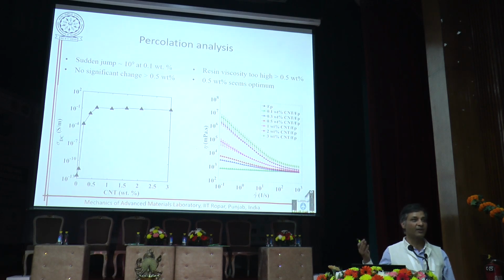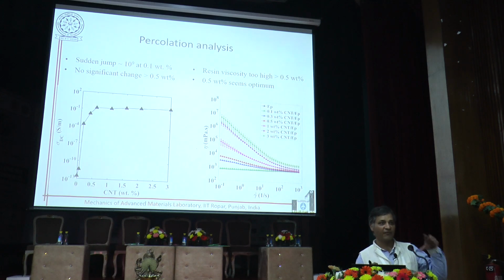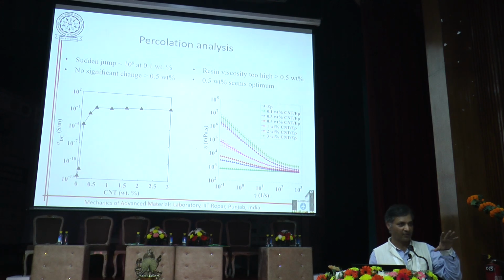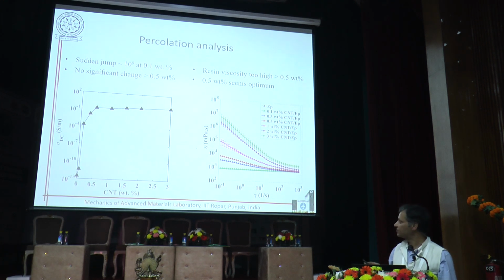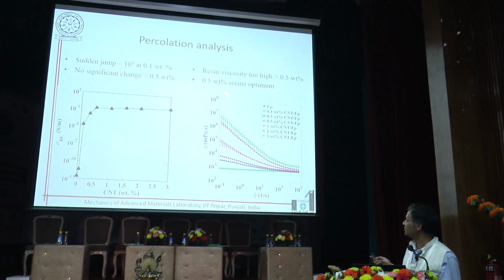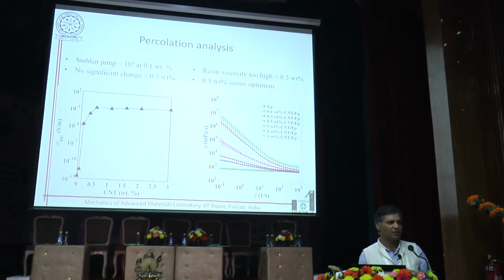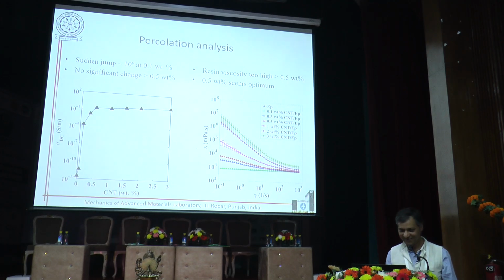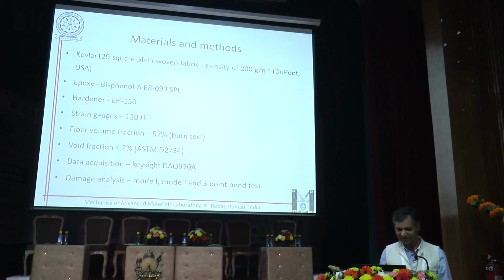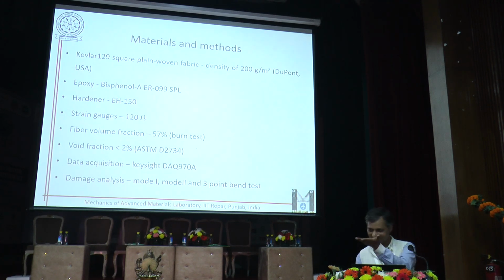And that has a very detrimental effect on the composite properties, because the wetting of the fabric will not be proper when your resin is more viscous. So you don't have a good bonding between the fiber and the matrix, or you have a poor debonding strength, right? So from this analysis we came up with 0.5% as an okay choice to modify the conventional resin system. Okay, so let's just skip it. There is a resin system that we have used, and then this presentation is used.